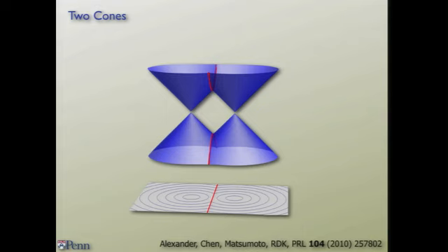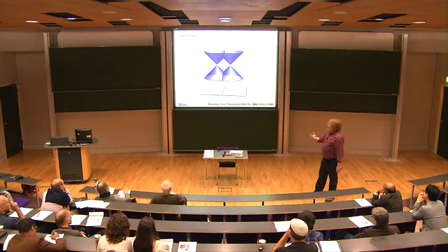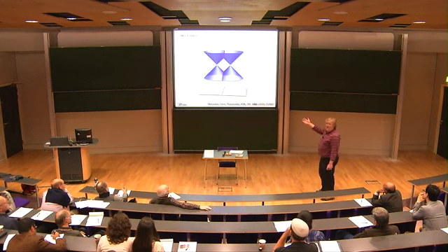Why is this line cool? The line is a place where the director changes its direction abruptly, right? You see the cusp? Because of that, the dielectric tensor controlled by the director has a jump in it, and that's what scatters light. That's the focal in focal conic. You see it without any cross polarizers because it scatters light.